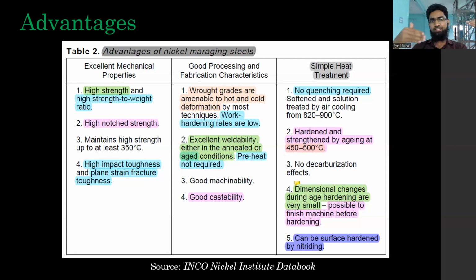I mean, hot working is done, cold working is done, warm working is done, and this is done without in-process annealing. So what generally happens is you have hot working being done, cold working being done, but at every step of this cold working cycle or hot working cycle, you have to have an annealing process to relieve the residual stresses.